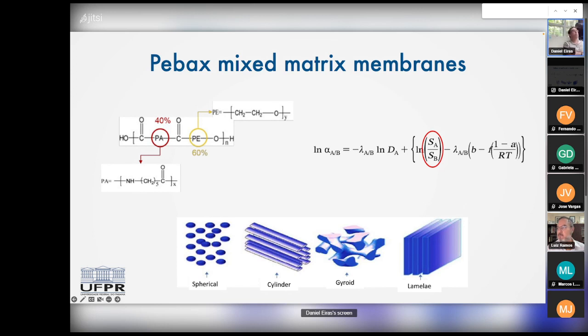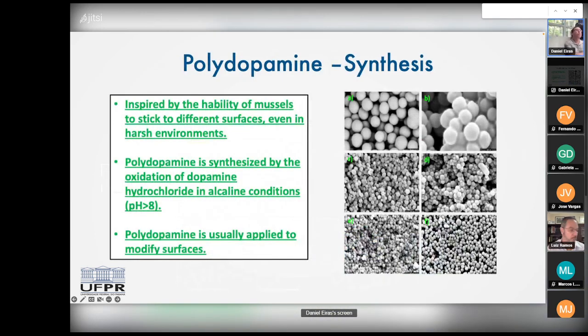Another interesting fact about PEBAX and copolymers is that they can form different morphologies depending on how you process them. So I've been working with this material and trying to modify it with different approaches. One of which was to use polydopamine, which is a natural polymer that was first synthesized inspired by the ability of mussels to stick to different surfaces, even in harsh environments. The synthesis of polydopamine is very simple. You can make it by oxidation of dopamine hydrochloride in alkaline conditions, pH greater than 8. And polydopamine is mostly applied to modify surfaces.